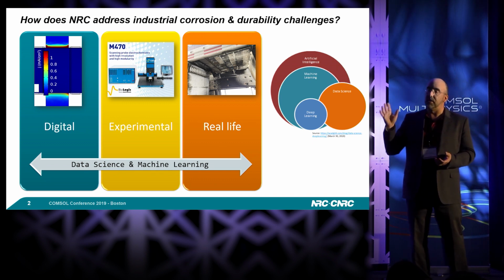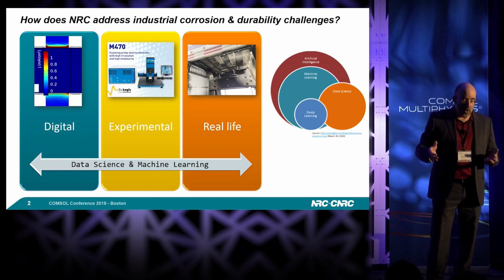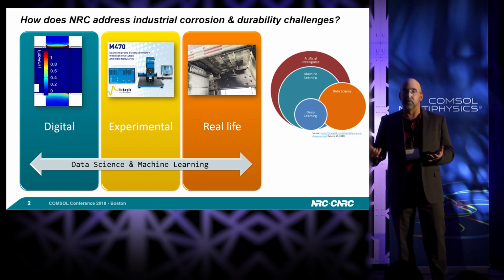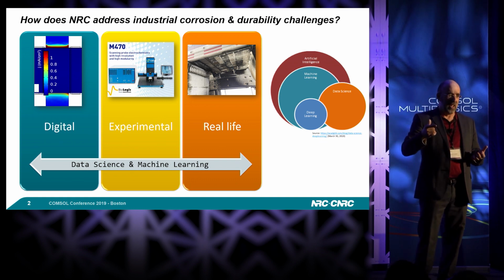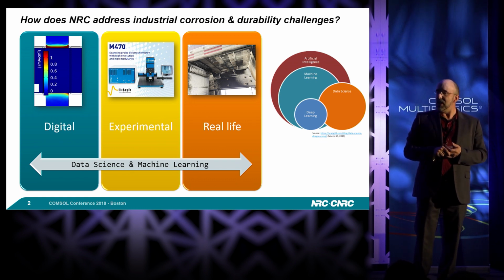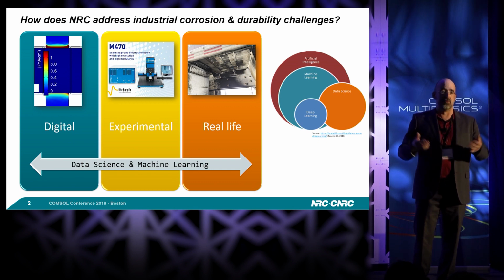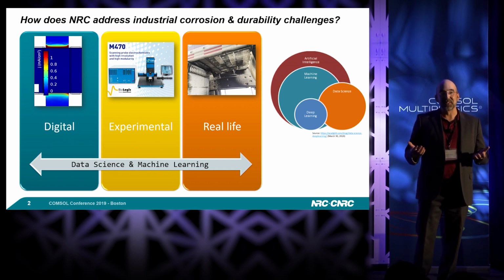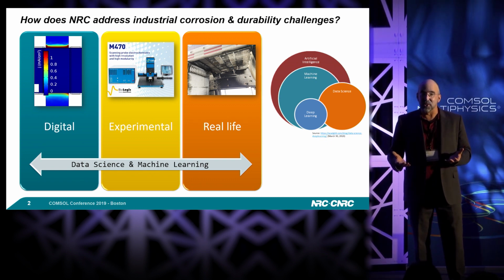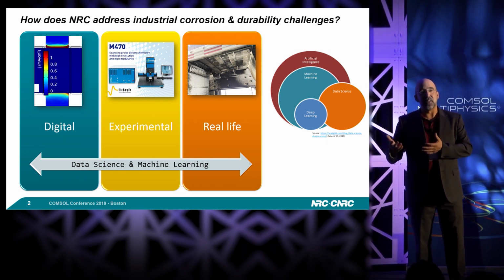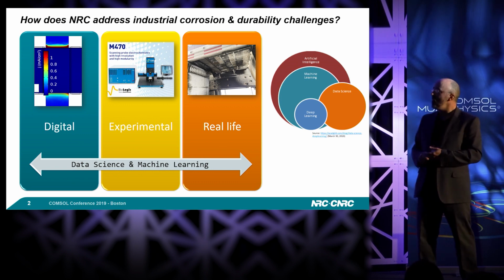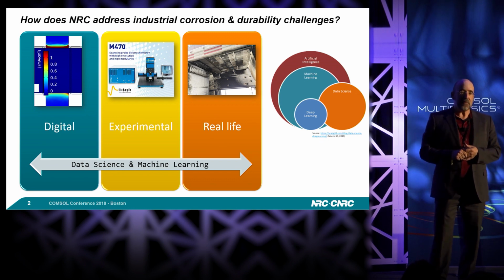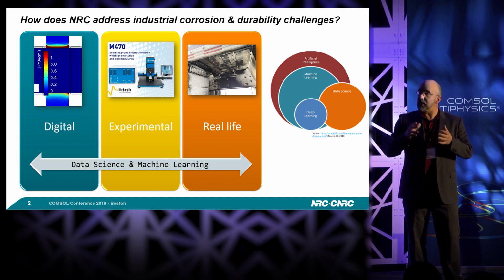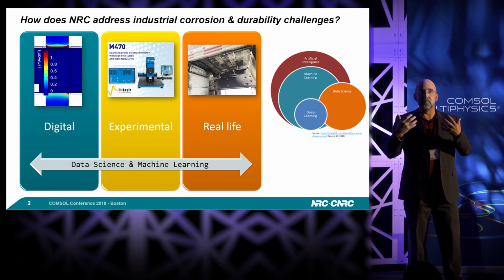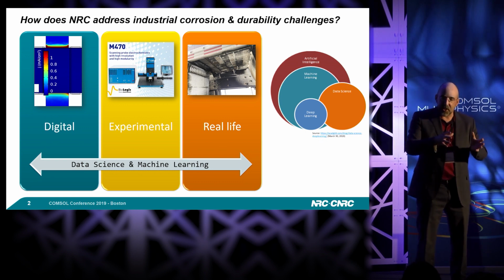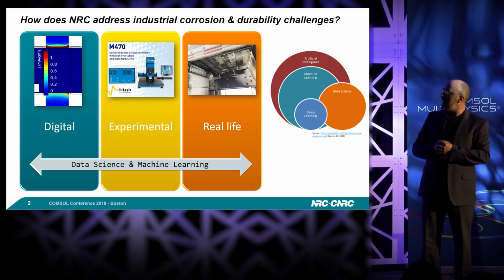When I started my career at NRC 12 years ago, almost on a weekly basis, I received phone calls from companies. They asked, okay, this specific standard, does it at least represent 5 years in service? I don't know. Nobody knows. 99.9% of standards do not rely on real-life situations. That's the reality. Then people started to say, okay, if salt spray doesn't work, we'll work with a cyclic corrosion test that better mimics real life. So you have a wet step, a drying step, and something like that.